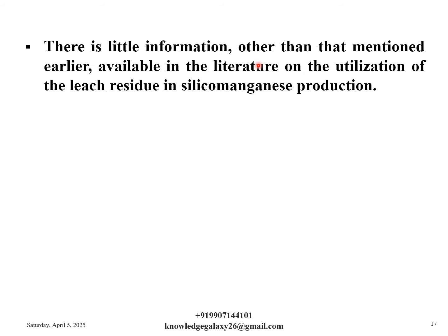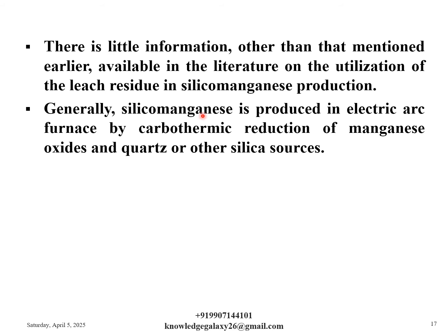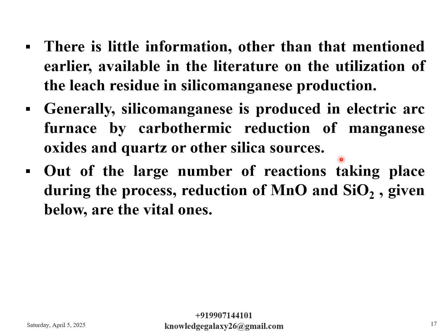There is little information, other than that mentioned earlier, available in the literature on the utilization of the leach residue in silicomanganese production. Generally, silicomanganese is produced in an electric arc furnace by carbothermic reduction of manganese oxides and quartz or other silica sources. Out of the large number of reactions taking place during the process, reduction of MnO and SiO2 are the vital ones. So the first reaction is MnO plus C, which gives Mn alloy plus CO gas.